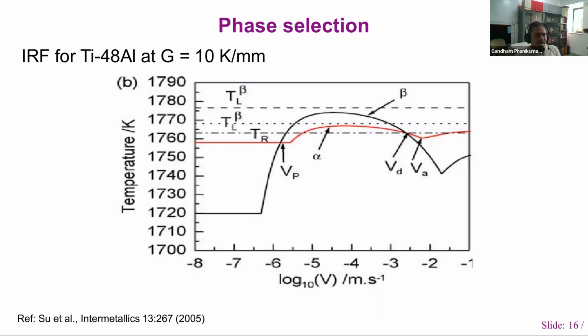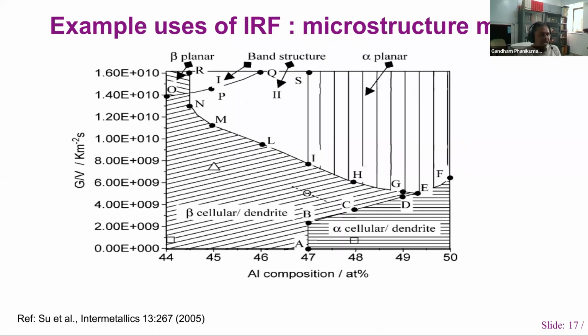Okay, and once you have that information, you can go on to actually change the gradient for which you have done the calculation, and then perform the calculations for every gradient, and thereby you can actually make a microstructural map. So that is a very powerful idea, because what we mean by microstructural map is, if you tell me the alloy composition and at what gradient and velocity you were doing the printing, I will tell you what phase will be there and what microstructure will be there.